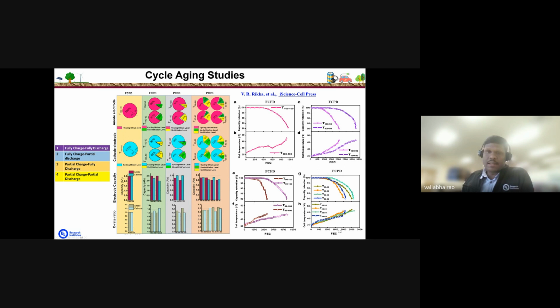These 9 test conditions meet the requirement for current EV applications, because operating from 80 to 100% of SOC levels can enhance the driving range of electric vehicles. By designing these test conditions, the yellow one is the unlithiation level of the cathode, which means we have utilized only 80% of the lithium from the cathode, and the remaining 20% of charge is left over in the cathode. We didn't cycle this 20% of lithium.